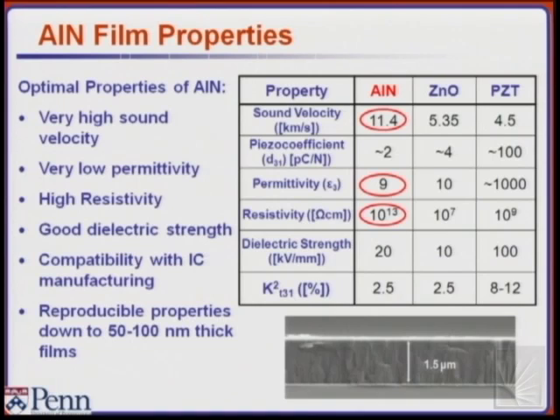But also, why aluminum nitride over other piezoelectrics? Here I'm making a comparison with the other piezoelectric materials out there, such as zinc oxide and PZT, which are probably the most widely used alongside aluminum nitride. The comparison is geared towards nanomechanical resonators and switches. If you're making other devices, maybe you have arguments in favor of PZT. But since you want to make high frequency devices, you probably want a material with a high sound velocity, and this is the highest. That means that for a given frequency, you can make a device bigger, so it's easier to make, ultimately.